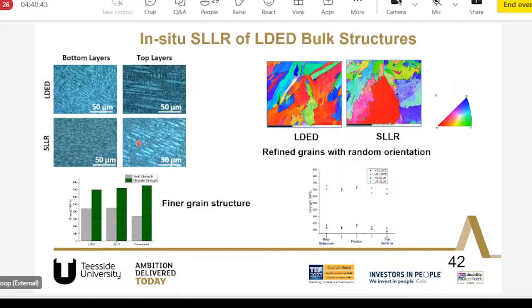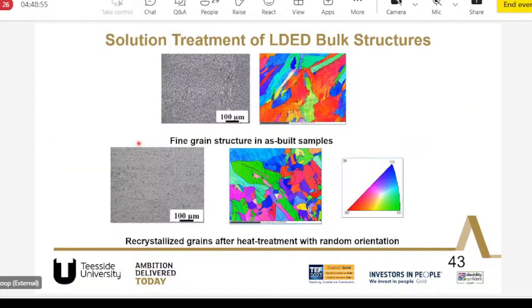I won't claim it as a very high refinement, but we could refine the grains to some extent, which would have resulted in an improvement in the mechanical properties in the base structure. Again, we did the grain structure analysis. The initial additive manufactured part has a fine grain structure in the as-built condition.